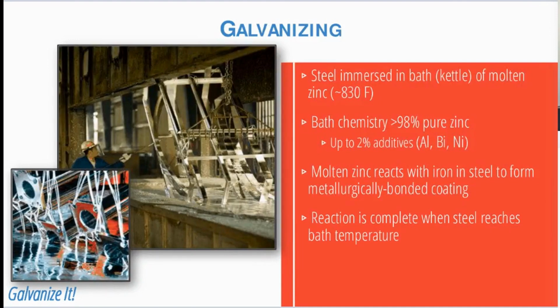During the actual galvanizing step of the process, the material is immersed in a bath of 98% pure molten zinc, maintained at approximately 820 to 850 degrees Fahrenheit. And while that steel is immersed in the galvanizing kettle, zinc reacts with iron in order to form a series of intermetallic alloy layers.